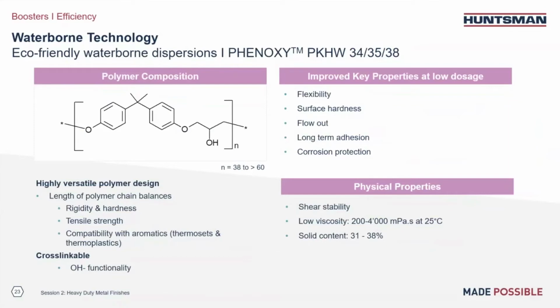In principle, those can be used as an additive, about 5% max, for adhesion promotion, for increasing flexibility, and for improving crack resistance without compromising hydrophobicity. In principle, the hydroxy functionality makes the material cross-linkable with molecules like isocyanate, anhydride, or silane. Their key property improved in an epoxy coating would clearly be anti-corrosion, due to the structure of the material.